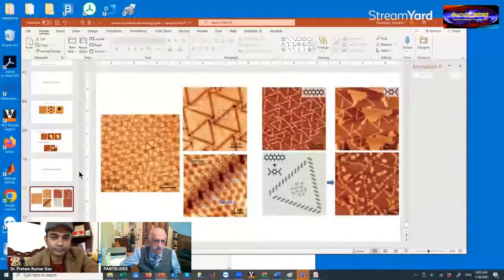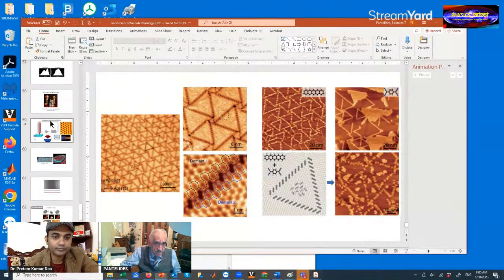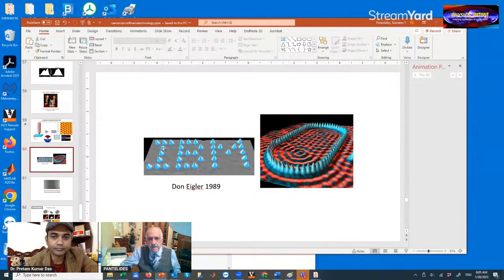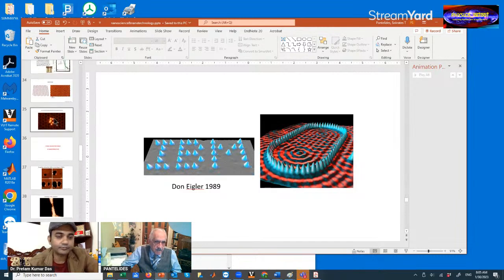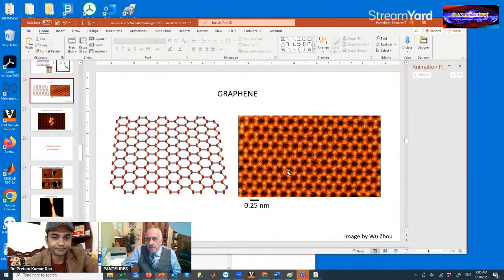It's in the images, because you have a scale in the images. In the STM, you image this, for example, by moving the tip. So when you image it, you have the tip coming down and you move it, move it, move it. So you know how much you move it. You know these distances. In the materials, you also know other things. If you go back to graphene, we know from X-ray diffraction and others what the distances between atoms are. So you can see here that this distance is 0.25 nanometers, a known distance of the atomic structure. And we're just imaging it here.